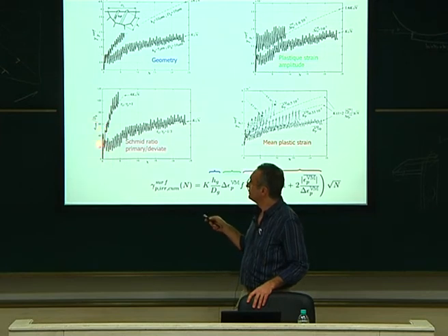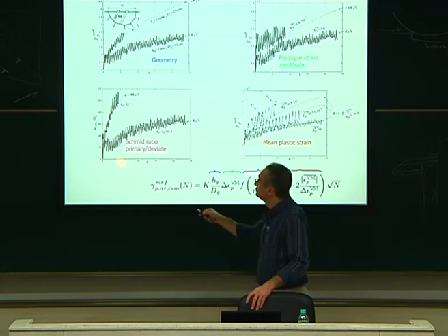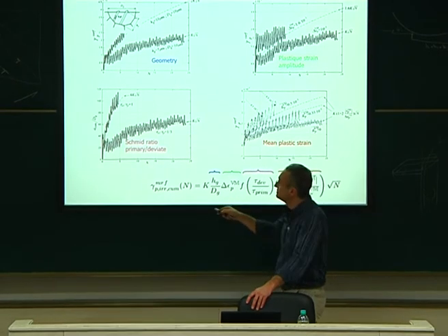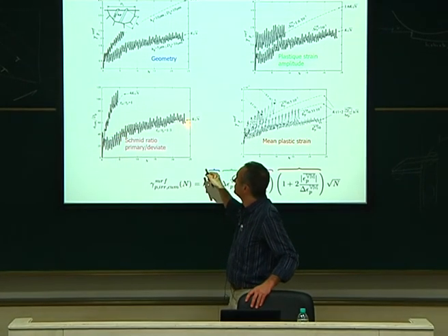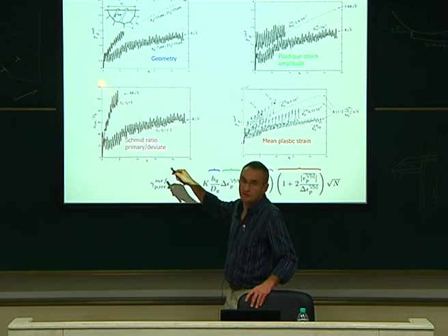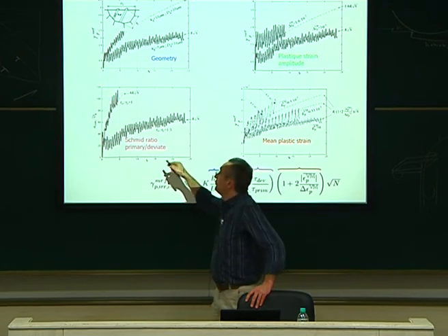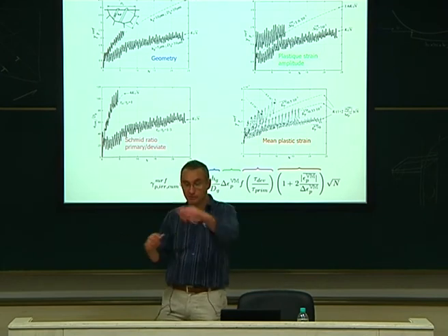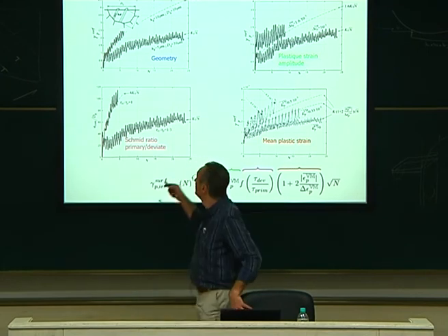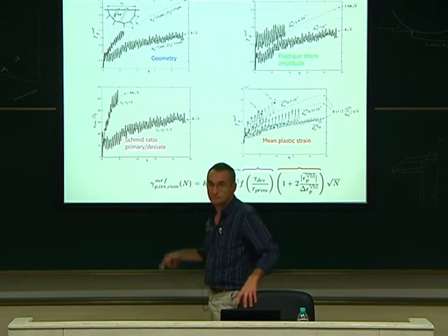What do you mean? If the stress is lower than what? So here, this is the number of cycles. After 5 cycles, this is my irreversibility for single shear. Here I have a much larger irreversibility. In other words, the extrusions are a lot higher. The extrusion height is a lot bigger, about 2 times bigger, factor 2.